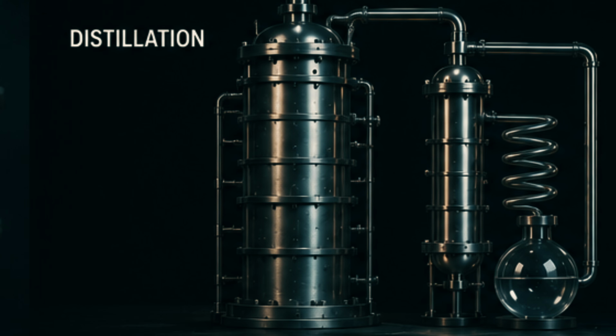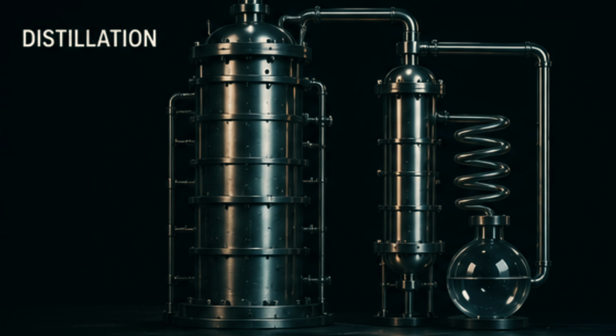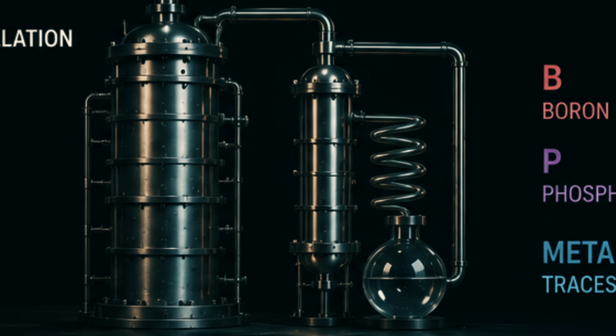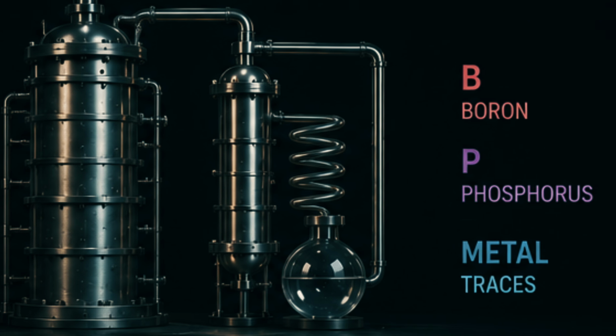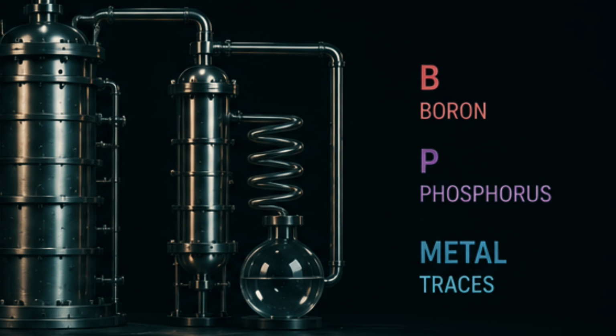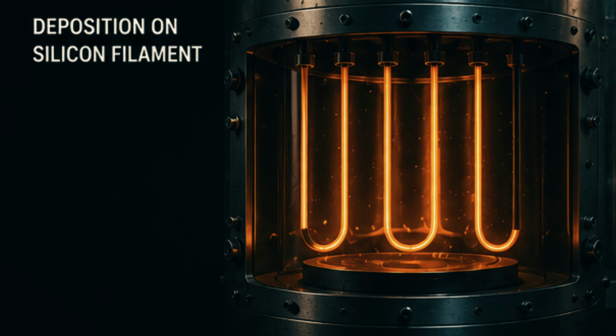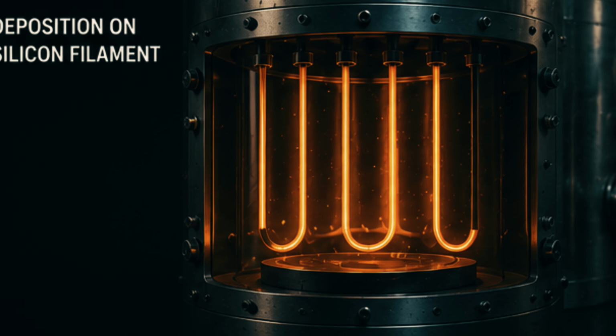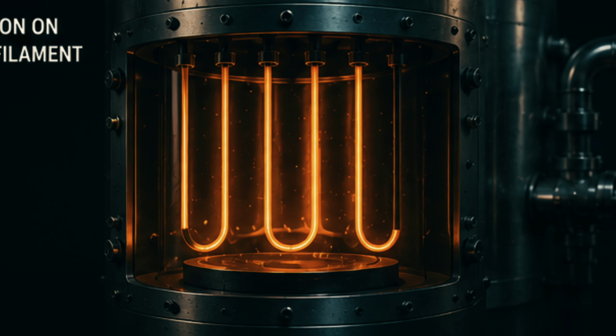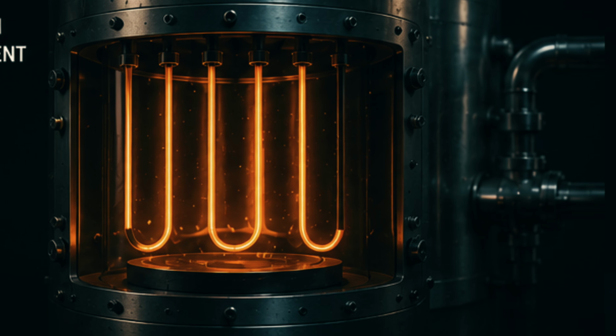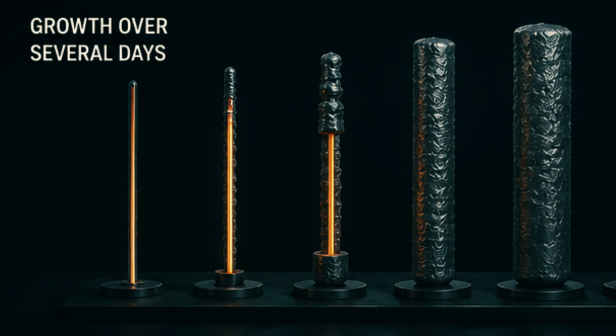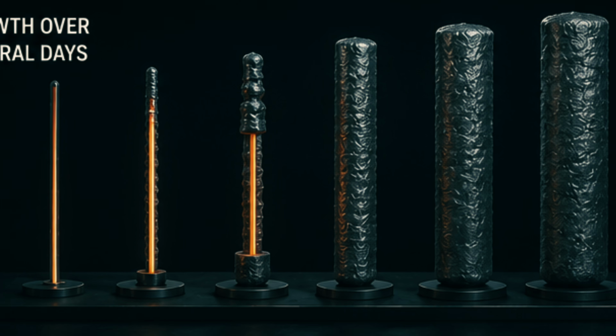That liquid is distilled over and over, boiled and condensed again and again, to strip out boron, phosphorus, and metal traces down to parts per billion. Concentrations so small they're almost meaningless to think about in everyday terms. Then the purified gas is piped into a sealed chamber and deposited atom by atom onto a thin silicon filament heated to about 1,150 degrees Celsius, glowing bright orange inside the reactor.